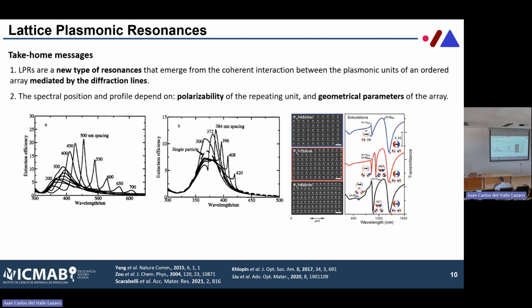So another take-home message that you should keep in mind for the rest of the talk is the first one: these are a new type of resonances. They basically come from an interaction of the localized resonances with the array. And this means that I can change these resonances acting on both the components here. So I can change the resonances by changing the polarizability of a single repeating unit, so basically changing the shape, the size, and the orientation of the particle. But I can also change these resonances by changing the geometry of the system.